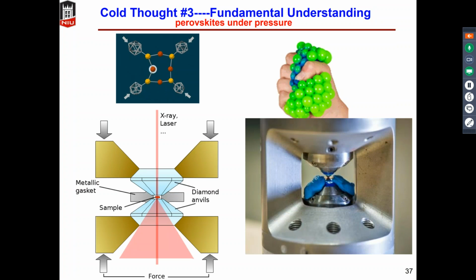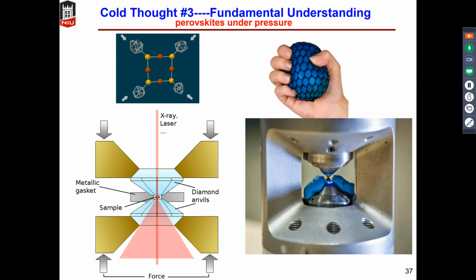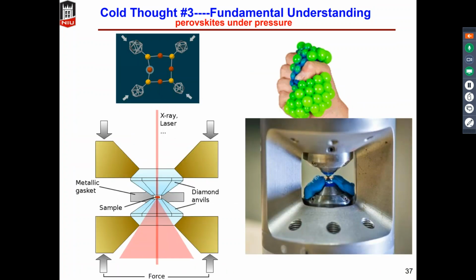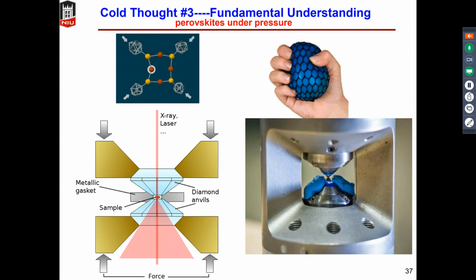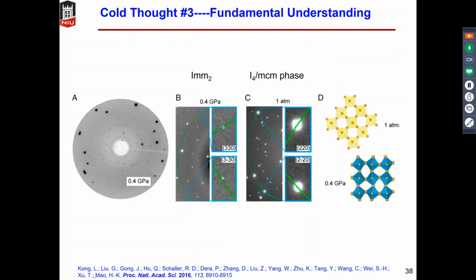And this is conducted by a pair of diamond anvils, and then it allows the in situ study of the structure by X-ray or photoluminescence spectroscopy. So we made these single crystals of MAPbI3 perovskite material, and at 1 atm we found that its phase is I4/mcm, but at increased pressure up to 0.4 gigapascal, it undergoes a phase change to Imm2.